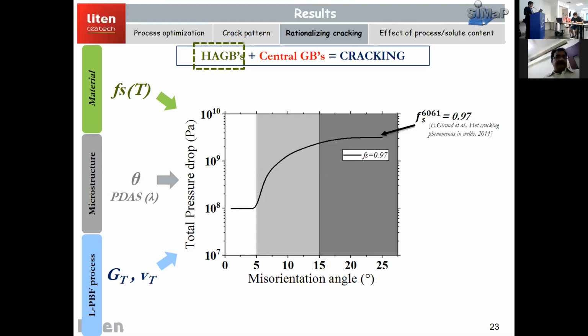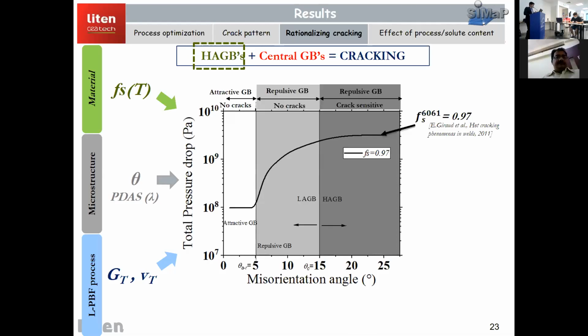So this clearly suggests that the pressure drop, in other words, the cracking tendency, is sensitive to high angle grain boundaries. For example, we know that the repulsive grain boundaries from 5 to 15 degrees will not be cracking, because in our experiments, we have seen that it occurs only after 15.